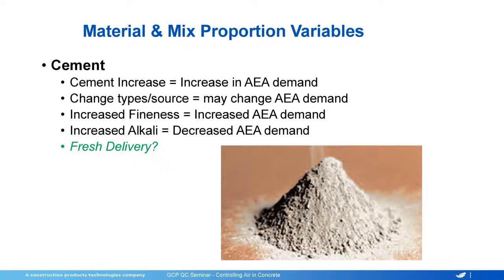Some of that was due to the fact that the water demand went up. And so as the water demand went up, we were using more admixture, less water, hard to get air entrainment. Okay, so one thing you can certainly look at, or two things you can look at on a MilCert. One is the Blaine, see how fine it is. You can also look at the 315. If the Blaine's changing and the 315 is not changing, then there could be something going on there with really fine particles. And then the alkalis.